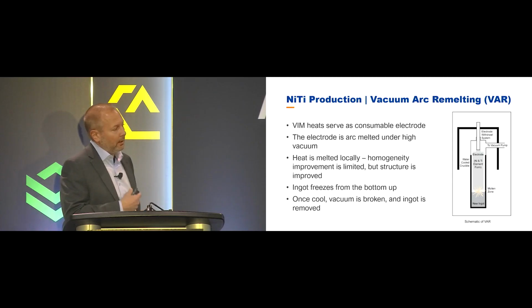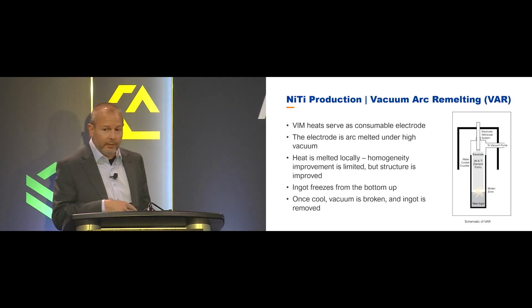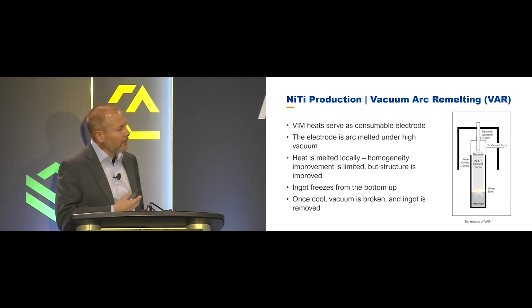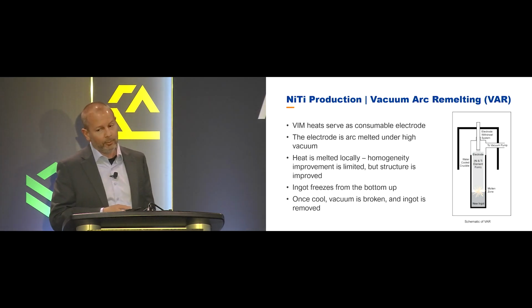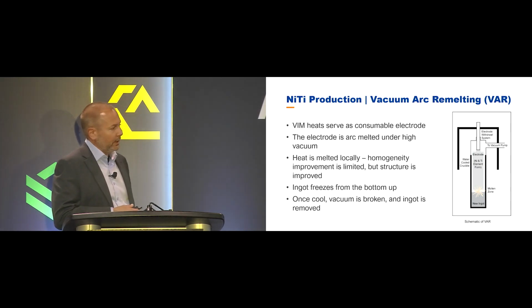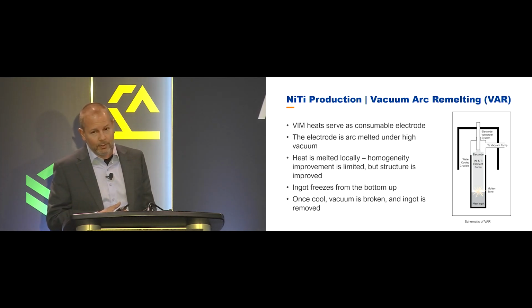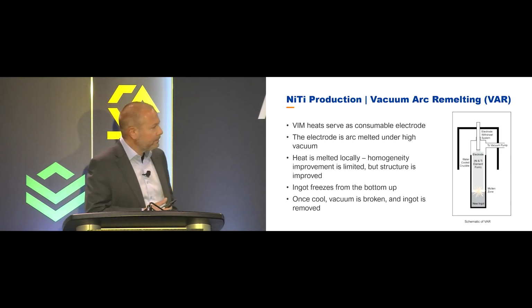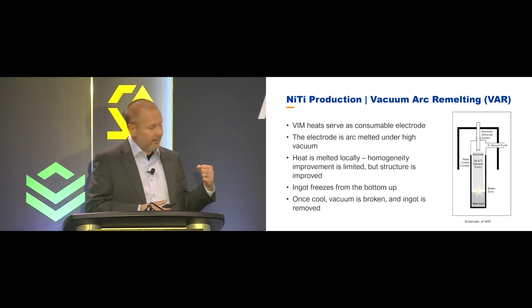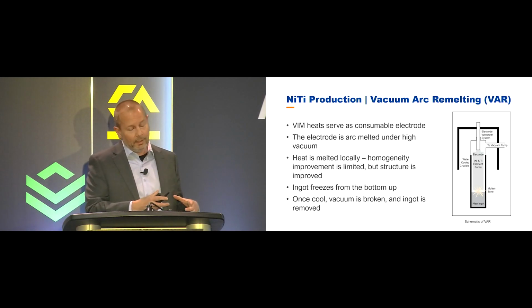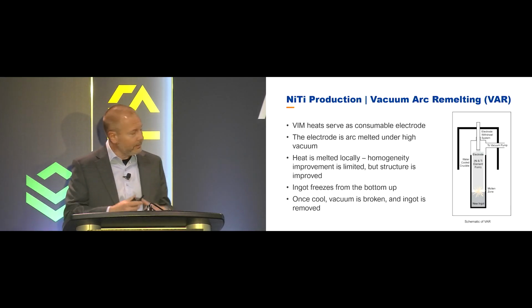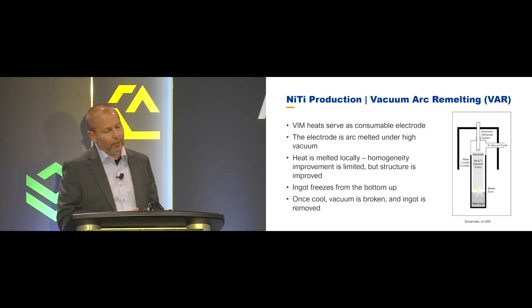From there, we take a number of those castings out of the VIM, we weld them together, and we will put them into a VAR process. So now we're using a different type of crucible. It's a copper crucible, and it's water cooled. And we have a stinger we put on the end of this electrode. It weighs about 2 tons, and we apply a lot of current to it, like 9,000 amps.